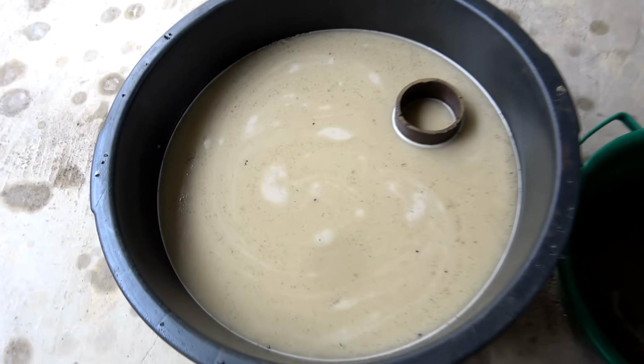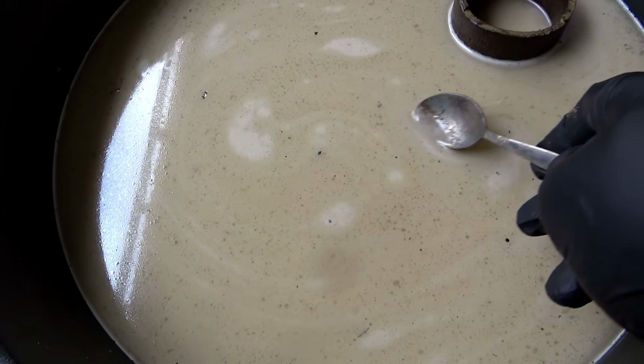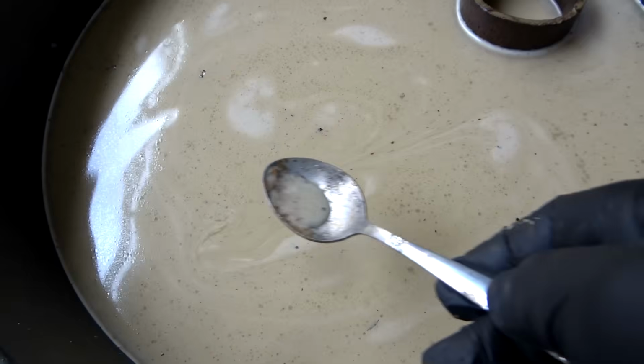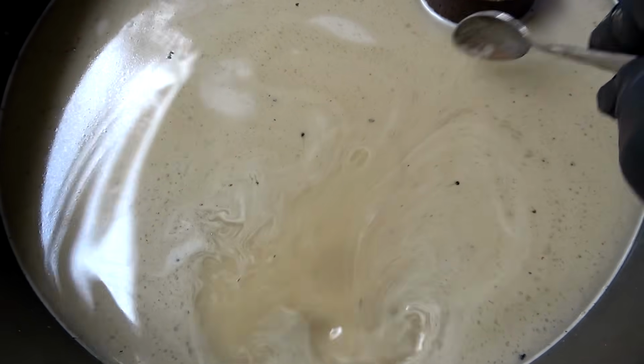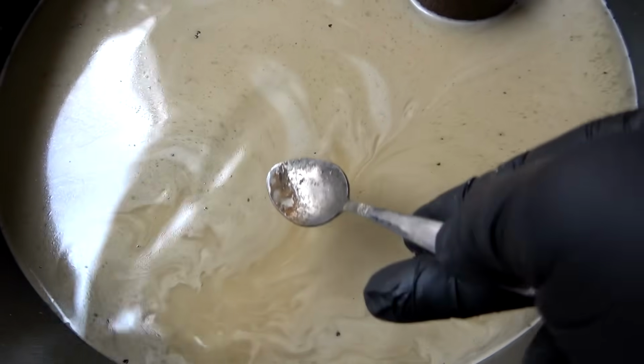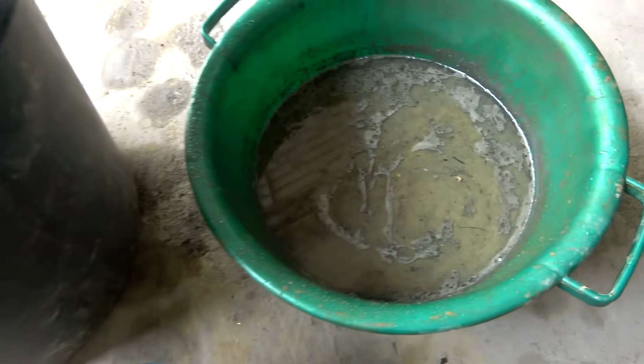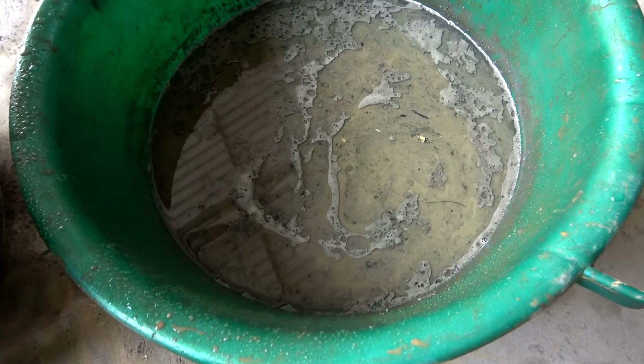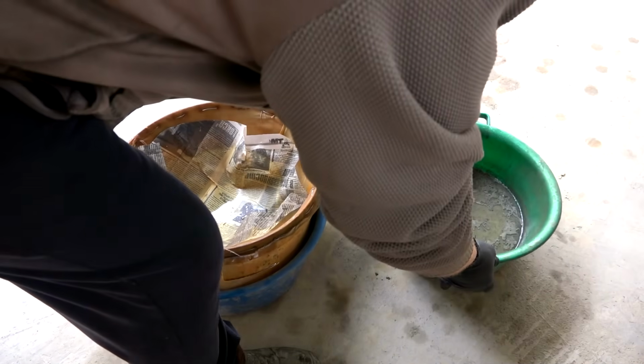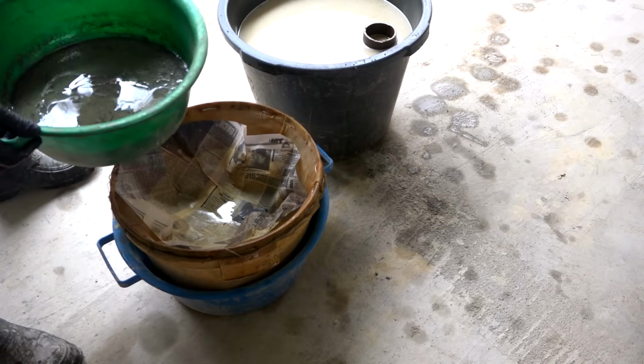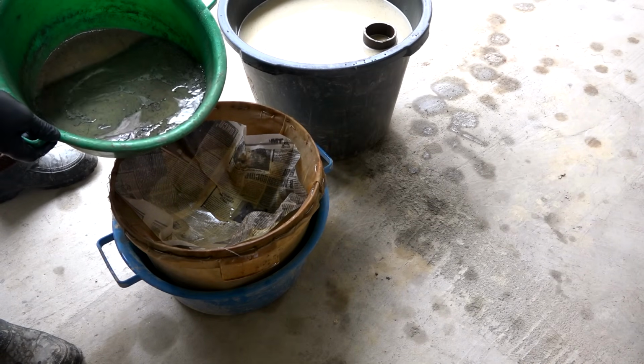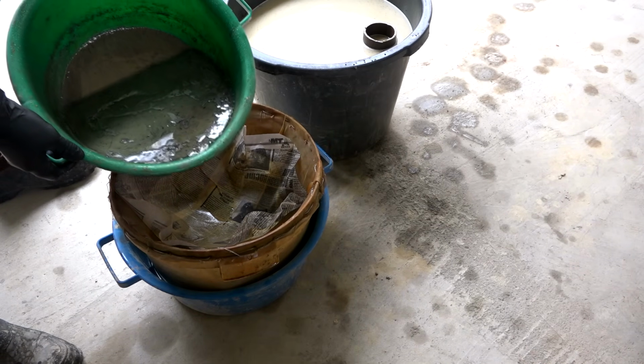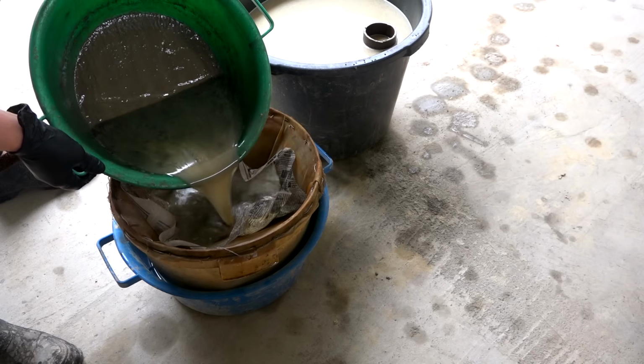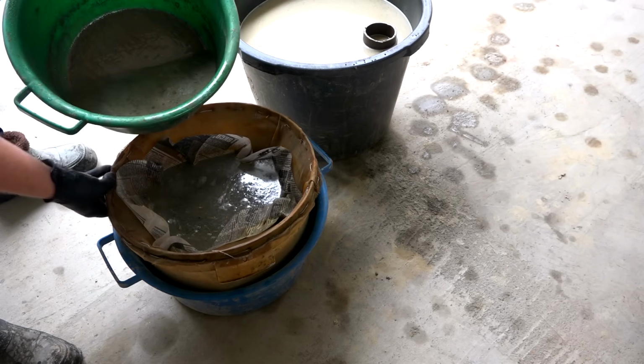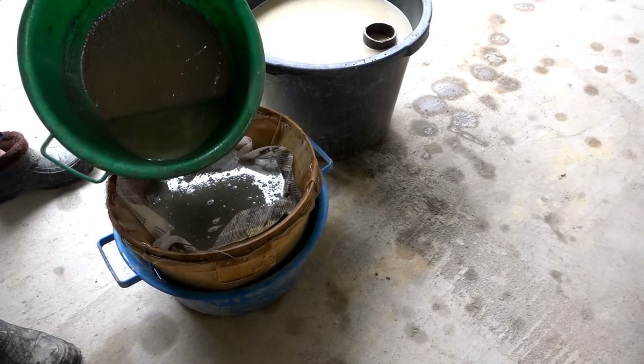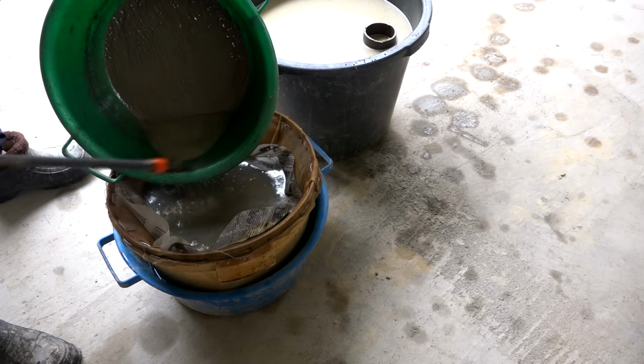After 30 minutes, I completed the flotation process, and it is clear from the pulp that there is nothing valuable left in it. A small percentage of diesel fuel floats on the surface, and there is nothing in it except some kind of white turbidity. A double enrichment has been obtained. This time, only a small amount of clay remains from the pulp, and I begin filtering the resulting flotation concentrate.